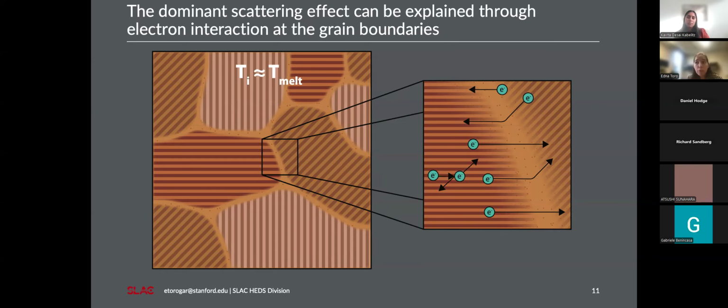So the electrons that are going really fast and bouncing around now encounter a slight change that doesn't necessarily decrease their movement by much. Therefore, the conductivity doesn't decrease because of this transition, and you end up with a system that behaves as you would predict for a bulk system. And that is mainly the lesson that we have learned here.